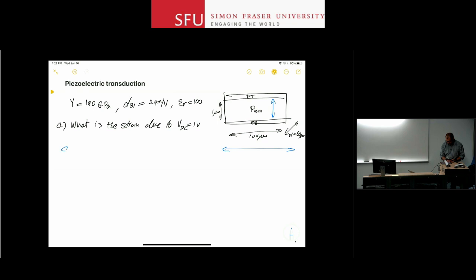you can show that the strain is D31 times the electric field, the vertical electric field, which is your V in divided by the thickness of the piezo material. So let's just call it TP, right? D31 is 2 picometers, 2 times 10 to the minus 12, times voltage of 1 volt divided by 1 micrometer for the thickness. The strain is going to be 2 times 10 to the minus 6, okay? So meters per meter or micrometers per micrometer. 2 ppm basically. This is a tiny amount of strain. Normally we cannot measure it, it's just too small. So at DC, I really don't get that much out of this device.